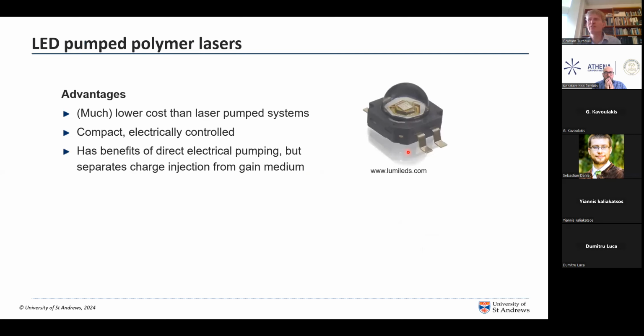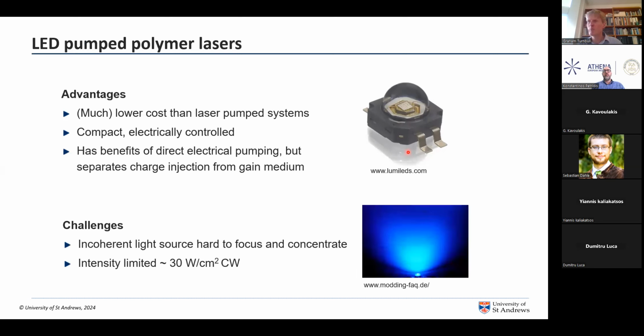So thresholds are low. Why do we need thresholds to be low? So if we want to not laser pump our laser, but we want to use, let's say, an LED, then there's some advantages and some challenges. So the advantages: this is compact and it's electrically controlled, and so it's moving towards an electrically driven laser, but in discrete components. But it has some challenges, that it's incoherent light, so it's hard to focus and concentrate, and whatever optics you sit in front of your LED, the best you can do is get typically 30 watts per square centimeter continuous wave. You can do better if you pulse, but that's typical maximum power density out of inorganic LEDs.